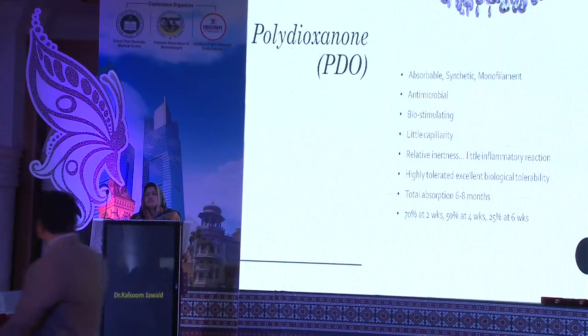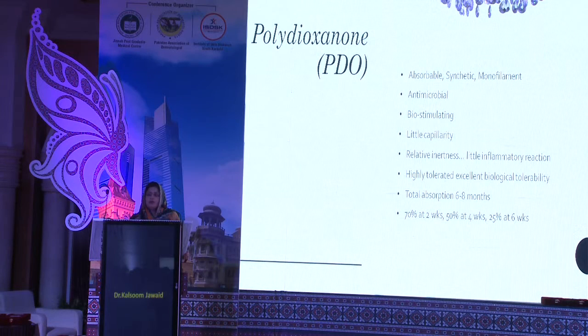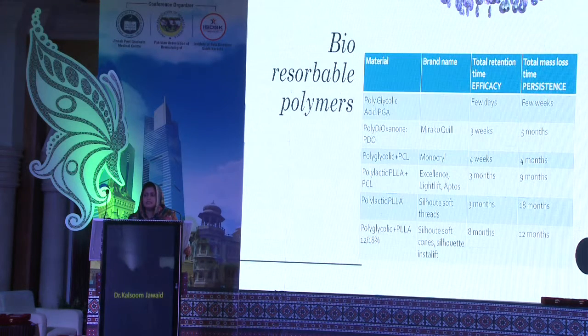PDO threads, conventionally speaking, are absorbable, synthetic, and monofilament. They have an antimicrobial effect and there are not many chances of infection. They are biostimulating to produce new collagen. They have little capillarity and are relatively inert. They don't cause much inflammatory reaction; the inflammatory reaction they cause is quite less than other substances. They are highly tolerated, with excellent biological tolerability. Their total absorption time is much better, 6 to 8 months. They lose about 70% of their strength at 2 weeks, 50% at 4 weeks, and 25% at 6 weeks.